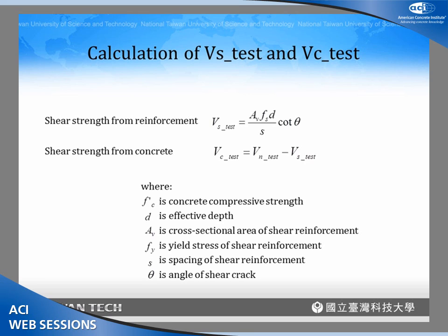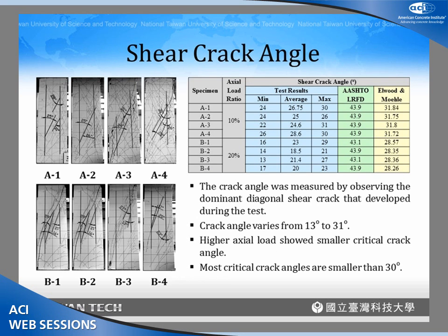The way we do that is, first of all, we estimate the shear strength contribution from the reinforcement using this equation, but we have to estimate the real stress in the transverse reinforcement. And I will show you how we did this later. And also from the test result, we are able to observe the cracking angle. So we get the real cracking angle to be plugged into this equation to calculate the shear strength contribution from the reinforcement from the test result. After we get that, then we plug the shear strength from reinforcement into this equation. Because we know the total shear strength, we will be able to calculate the shear strength contribution from concrete.